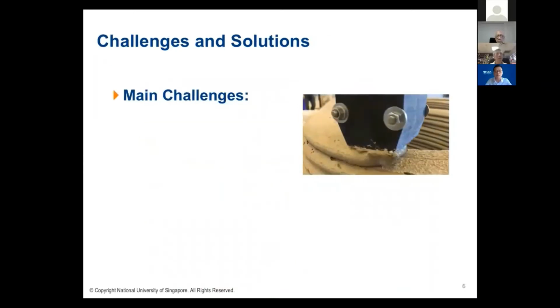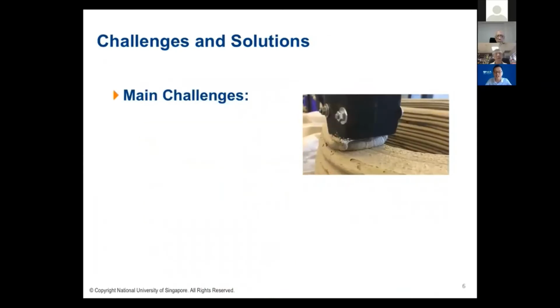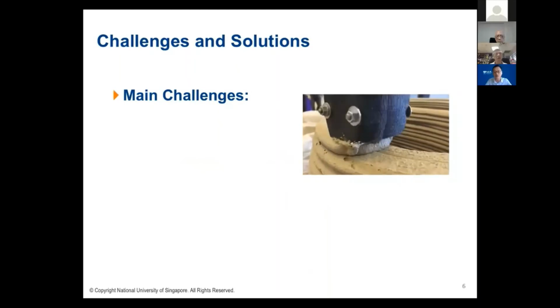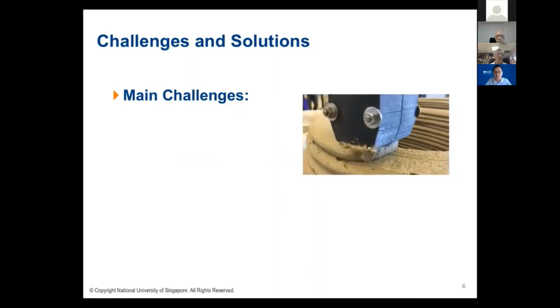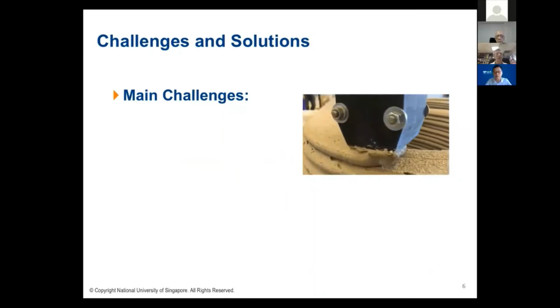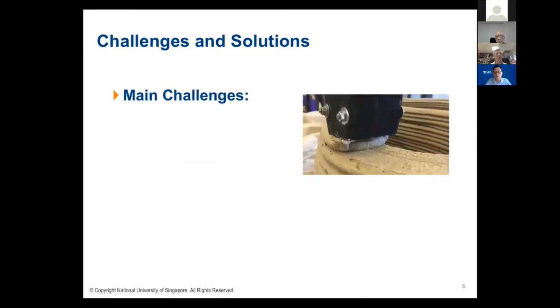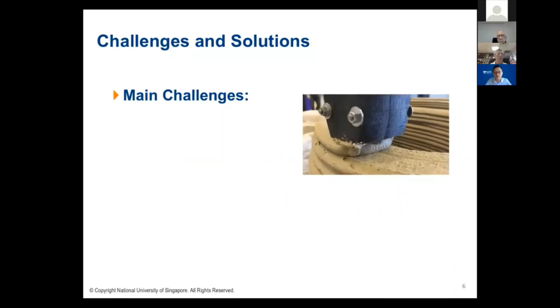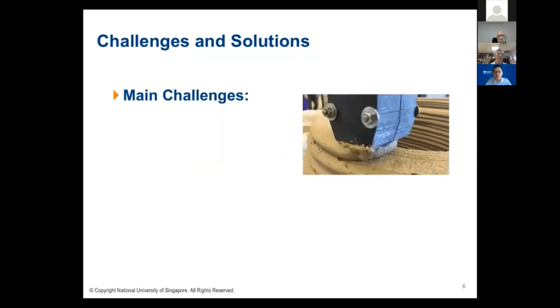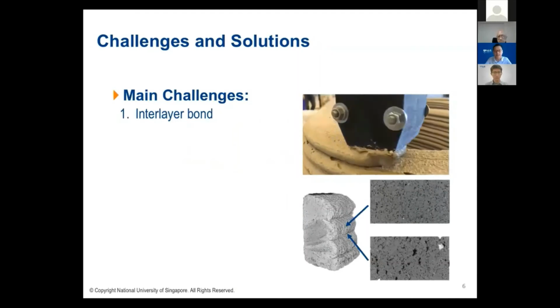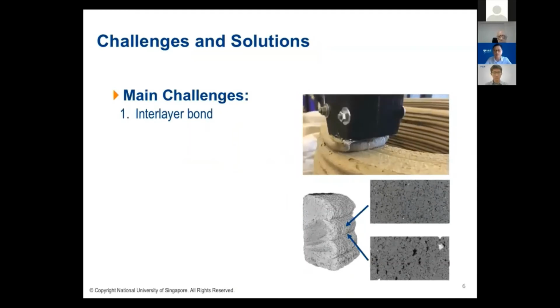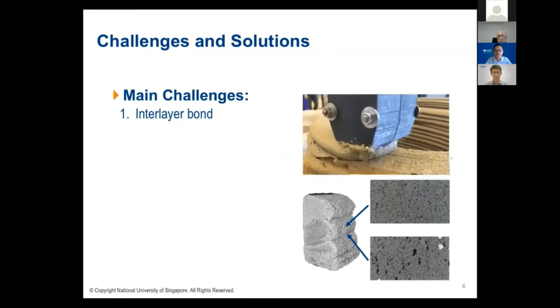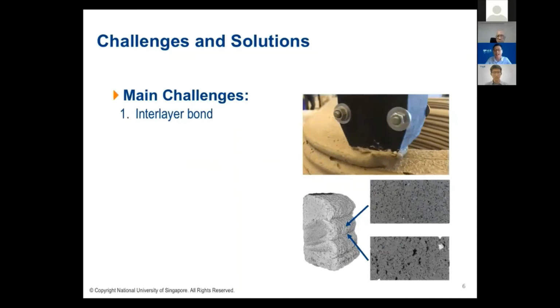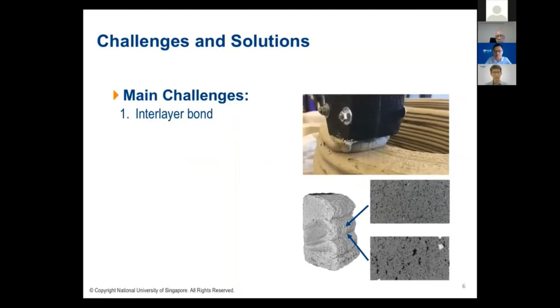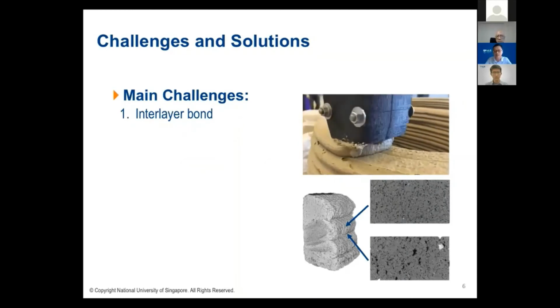And now I'm going to introduce you a few main challenges, because this is a new area, so there are lots of very critical challenges. And this animation on the screen shows you a very typical layer by layer 3D printing concrete. And the first challenge is the weak interlayer bond. I think Prof. Tam just now have introduced the cold joint for different concrete lift. And 3D concrete printing has a lot of cold joints because the fabrication is layer by layer.